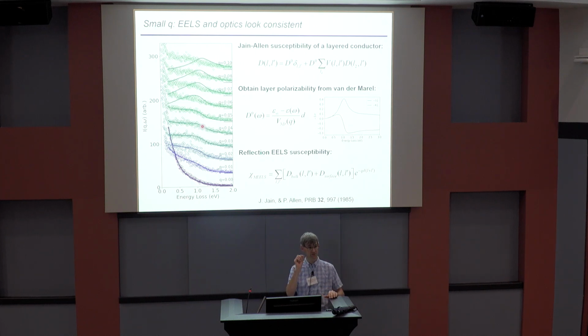Okay, so the real question is what happens at larger Q? And you can see what happens. For momenta bigger than about 0.05, you start to see deviation between the EELS data and the optical data. So if you simply trusted optics to be relevant at all momenta, you'd expect to see a plasmon that disperses. But what the EELS does is it turns into a continuum that's basically frequency independent.